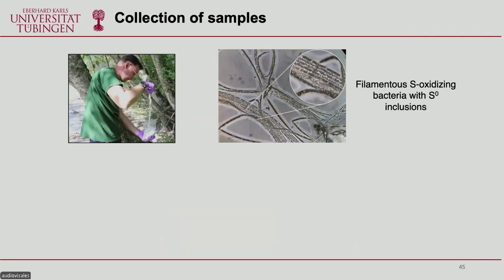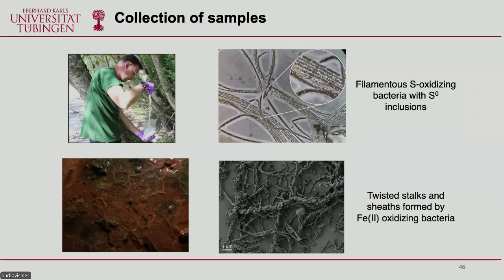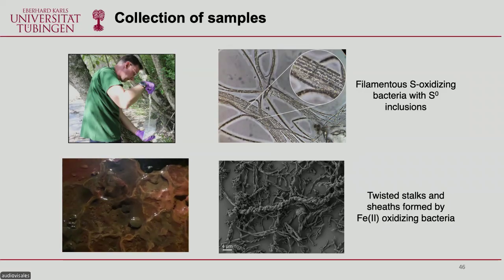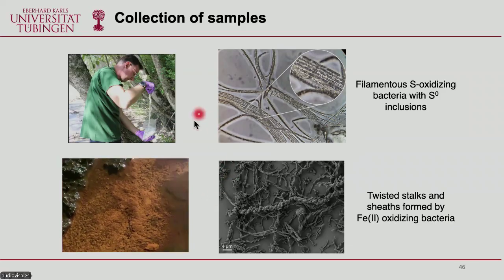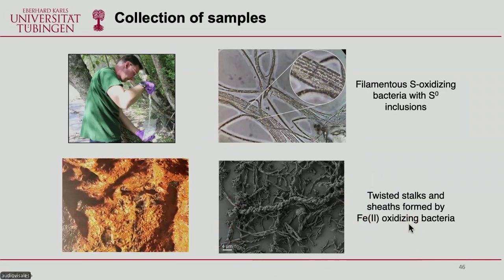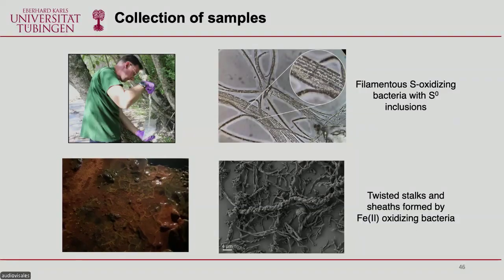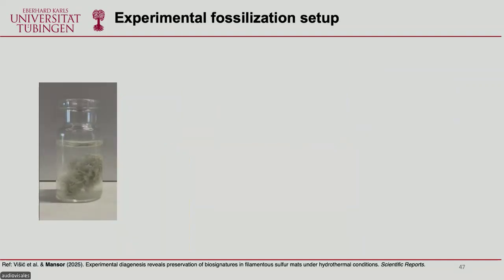And to do that, we need to first collect the samples. So we need to go to environments where we can find the samples. And so this is one stream in Switzerland. It's a sulfidic spring. It's very cold. It's in the Alps. But here you can see that we can collect lots and lots of filamentous microbial mats that you can just scoop up with your hand. When you look at them under the microscopy, you see these clear filamentous structures, and you see inside that they have these bright structures. These are all elemental sulfur inclusions. Then we also have this field site in the mines about 2 hours away from our location. And you see these iron deposits just fully covered the mine. The puddles in the mine as well as on the walls. And looking at the microscope, then you see these twisted stalks and sheath, which are typical for iron oxidizing bacteria. So we collect them, we brought them into the lab, and then we put them under different conditions.